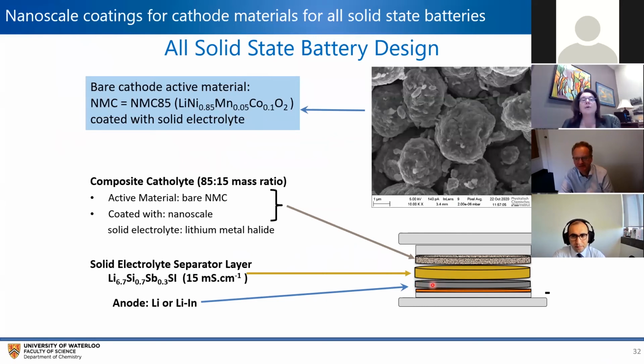And you might say, well, shouldn't your solid electrolyte inhibit the penetration of dendrites? In practice, it probably would, but you have to actually make this electrolyte almost completely dense. In other words, completely compress the grain boundaries, because the little dendrites will literally sneak right along these grain boundaries. And we have not yet managed to get 100% dense pellets. And so we simply cheat by, at least in our solid state cells, using a lithium-indium composite, because that is very highly resistant to dendrite growth, and it allows us to sustain these higher current densities. Now, that's not to say that we're stuck there. By no means are we. We will solve this problem, but it's kind of a worldwide problem, not just ours. Yeah, that's right. But it's wonderful work. I just thought, that was a little thing.